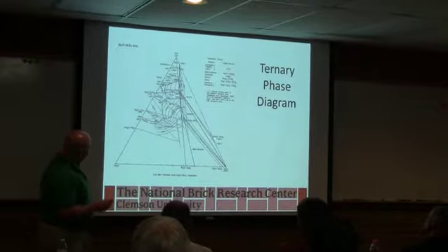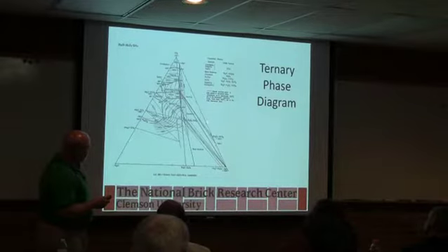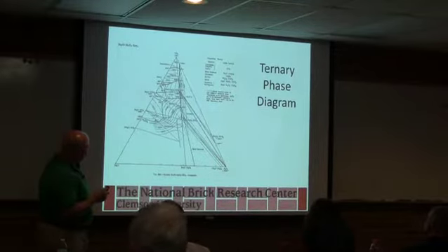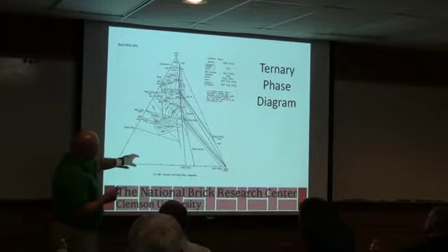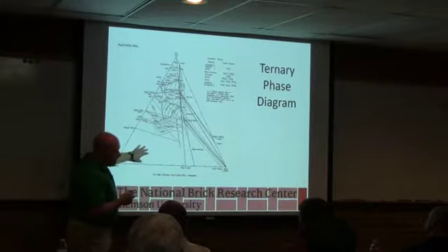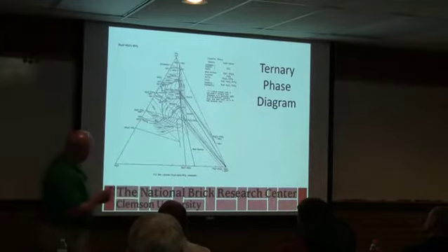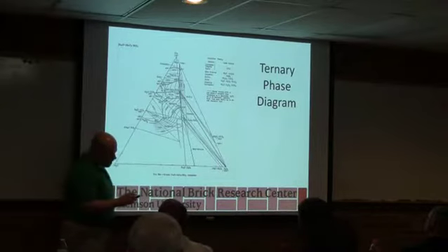If we were looking at our blend of raw materials, so we said it's roughly 65-70% silica, alumina being the next biggest thing. Our firing temperature is somewhere in here, so in excess of 1600. We add some sodium, and that starts, and this is all in Celsius. Usually you're looking for the lowest. These are called either eutectics or peritectics. We won't go into that. You can see these same kinds of diagrams when you're looking at solders. They use this same idea when they're blending a solder so it melts at a low temperature. You can start to see liquid as low as 700 degrees Celsius. So just an idea of how fluxes work.